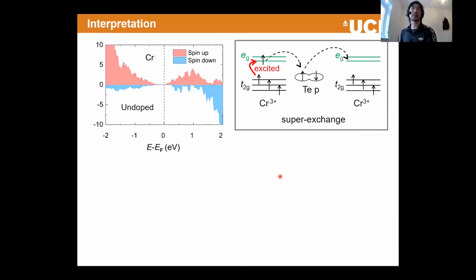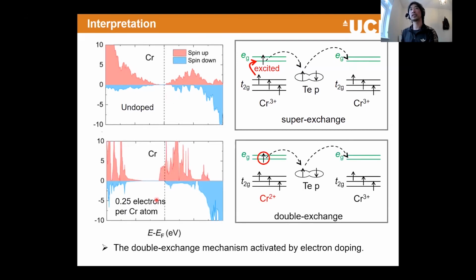Okay, so the interpretation of this is that, as I already explained, this is the insulating or semiconductor behavior, but once you dope and add charge, then the Fermi level goes inside of the conduction band. In this case, we can populate a lot of conduction electrons inside this conduction band, and then that can promote hopping around, and that can really facilitate the double exchange mechanism. And because of this kinetic energy reduction, we can reduce the total energy as a whole. That's the driving force of the ferromagnetism within this doped regime.